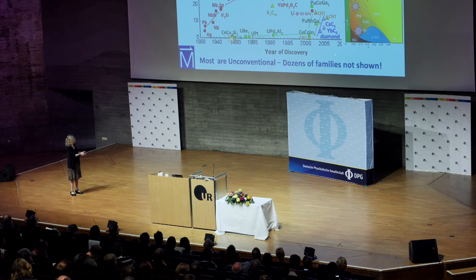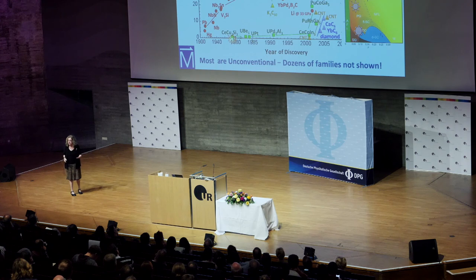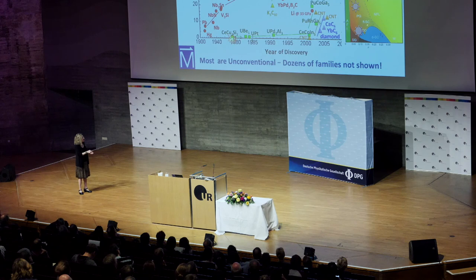So let's talk about the unconventional superconductor phase diagram. This is temperature up here, and this is a thermodynamic variable. It could be doping, it could be pressure, it could even be magnetic field. But what we have here is that on the left side, you have a bad metal that's typically antiferromagnetic or an insulator in the case of the cuprates. On the right side of this diagram, at the high doping, high pressure side, you have pretty much a normal metal, a Fermi liquid, that you can describe.